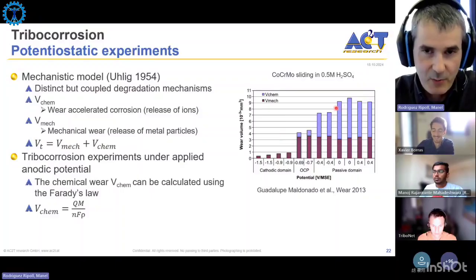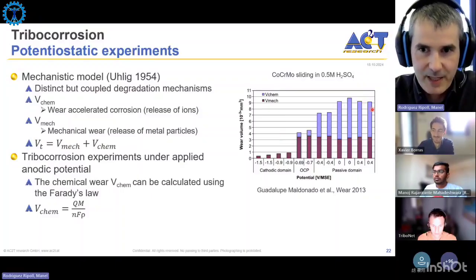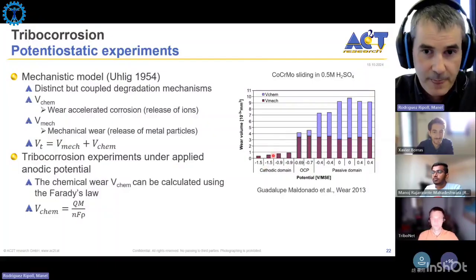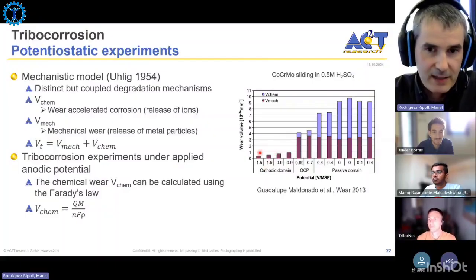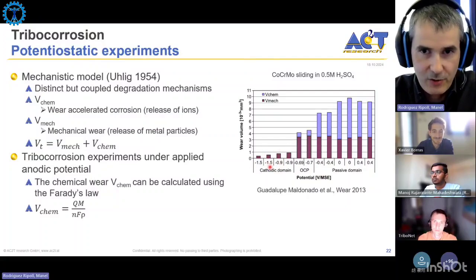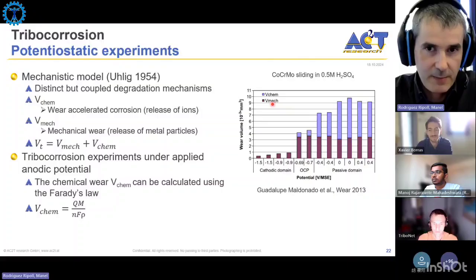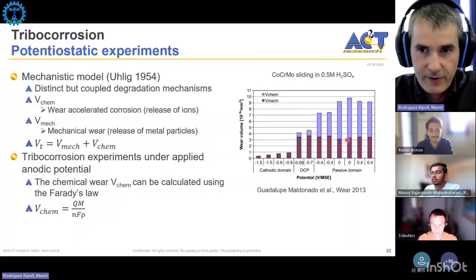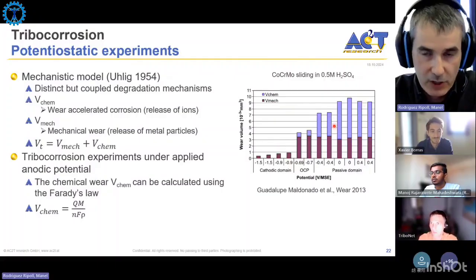So basically we're promoting the formation of a thicker layer when we apply a passive potential and then automatically destroy. So we have here disrupted synergy. So we have the highest wear here in the passive domain. In the cathodic domain, we have the lowest wear. And since we are under cathodic protection, we are inhibiting the anodic reaction. So we have here mostly wear that is imparted by mechanical wear, and as we move towards the passive domain, the contribution of chemical wear gets more important.